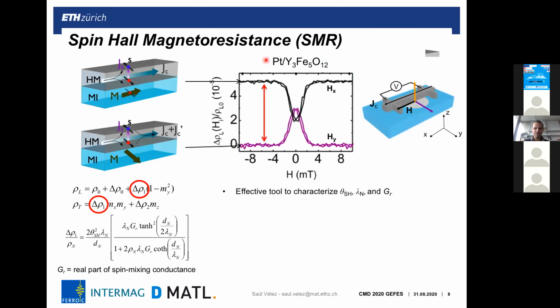This is demonstrated here in platinum on top of yttrium iron garnet, in which you can see that depending on the direction of the magnetic moments, when they are perpendicular to the spins, you have a high resistance state, and when they are parallel, you have a low resistance state. The amplitude of this effect is given by this formula. In the first approximation, you just consider this parameter here, the real part of the spin mixing conductance.